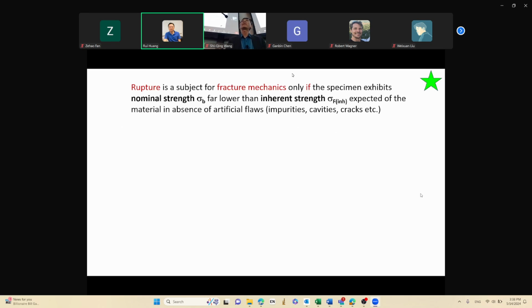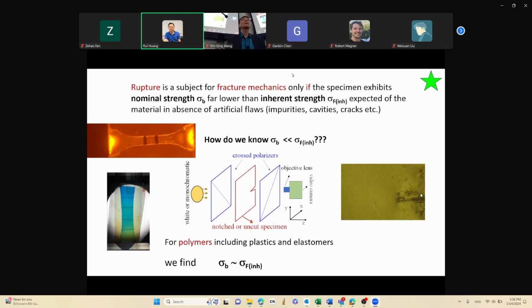So in any case, fracture is not a fracture mechanical problem if we don't blame flaws. In other words, fracture only is a problem if our nominal strength is much lower. I came from polymer physics, equipped with some understanding of our brittle glassy polymers, that I know these two stresses might be comparable. That was my starting point. If that's the case, in the uncut case, there's no business in fracture mechanics. But fracture mechanics does come back because when you have a large crack, that's when things happen.